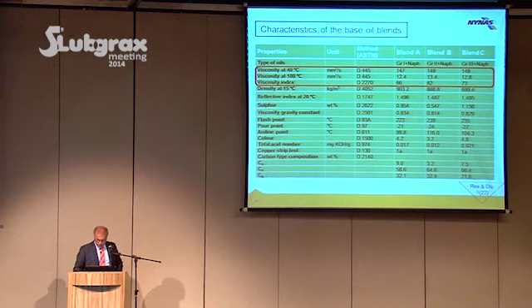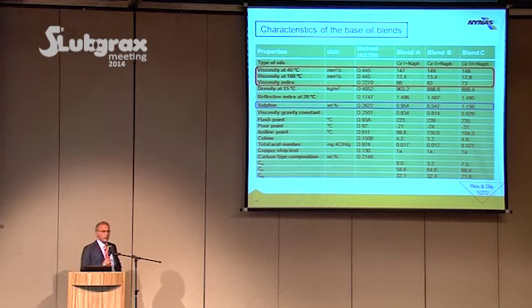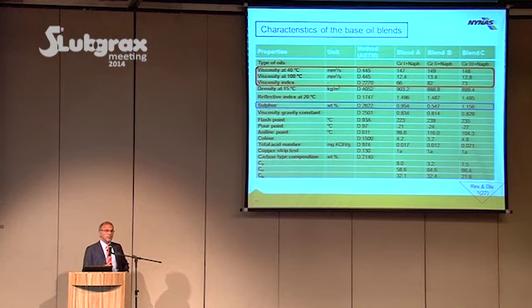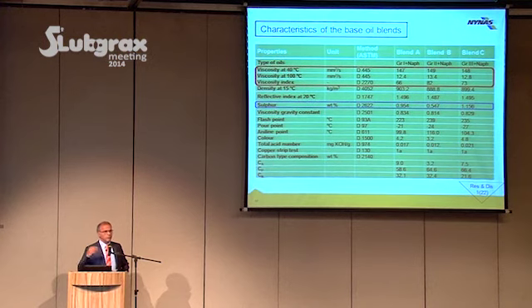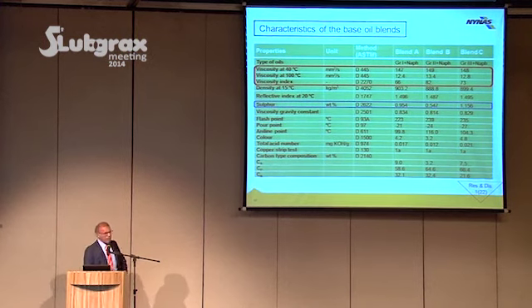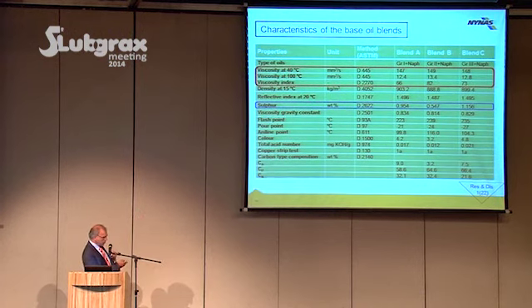Anyhow, sulfur content, this is interesting because we have found that a certain type of sulfur molecule has a great impact on the oxidation stability of the final product in the application, and that kind of sulfur has almost zero impact on corrosion. So it is also interesting. So this high amount of sulfur which you can see here is coming from the naphthenic oil which we used for this particular study.